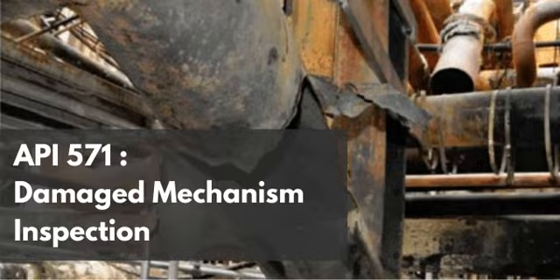But, from an engineering standpoint, that's cold comfort. Very cold comfort. Because even if the rate of deepening slows down, the damage is already done to that outer layer. Exactly. The rate might taper off, but by the time it does, the outer wall is already compromised, severely brittle, and structurally useless. You have lost your sound metal thickness regardless of the slowing kinetics.